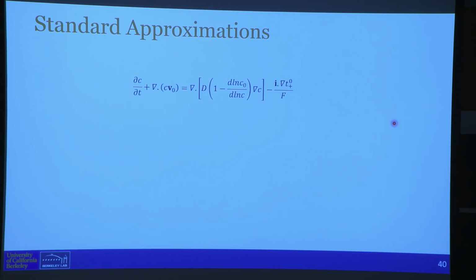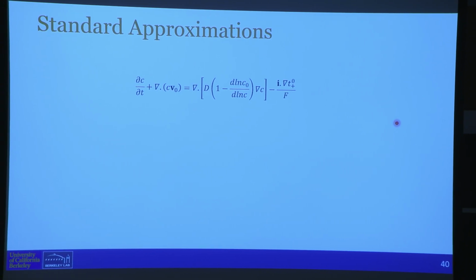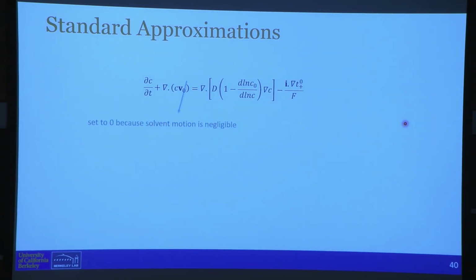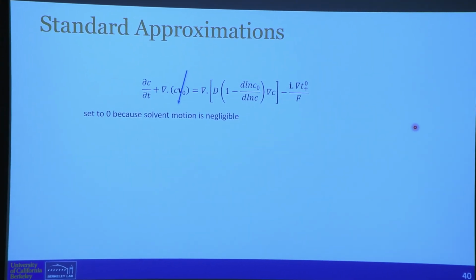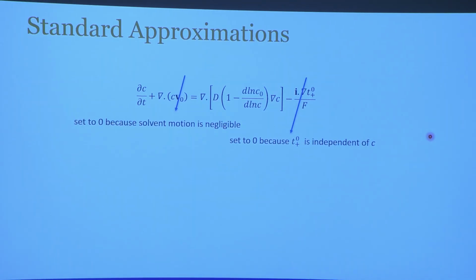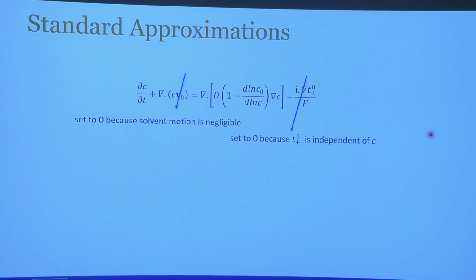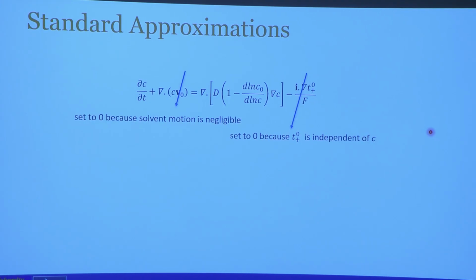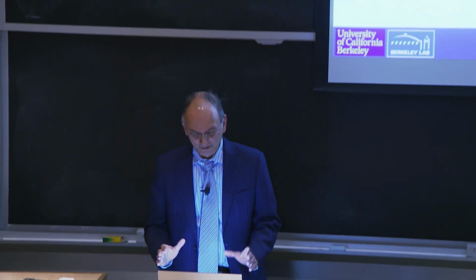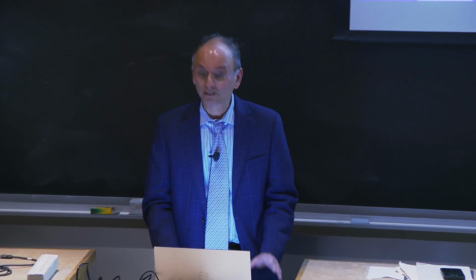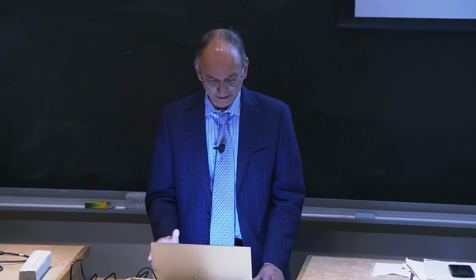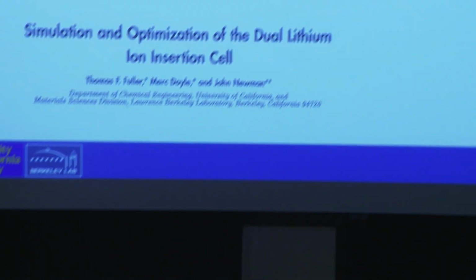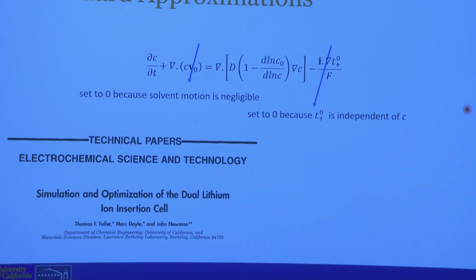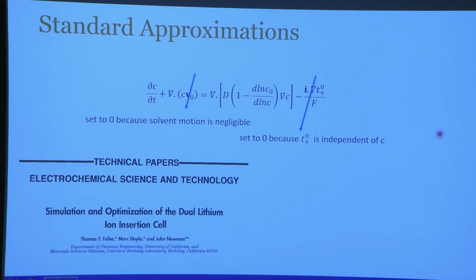There were some standard approximations, I would say, that were made in this field up to about 2016 or so, which is to say the solvent is not that important, and so we'll set that term to 0. And that the transference number, which is a ratio of currents, it turns out, is also independent of concentration. It's a very hard thing to measure, big error bars. So you say if it's independent of concentration, that term drops out, and it just boils down to diffusion. And this is the only theoretical paper in the Nobel report on lithium-ion batteries. And that's the assumption which is used to model all lithium batteries. Okay?